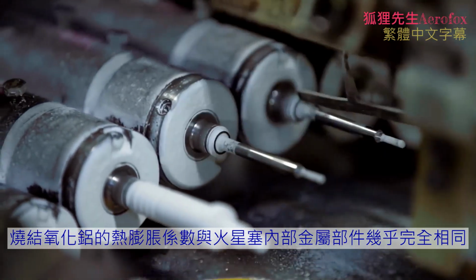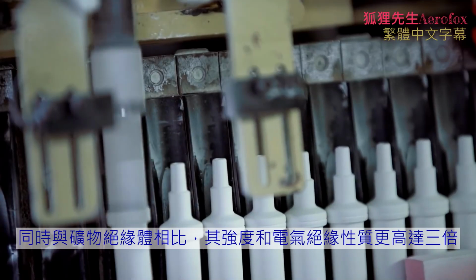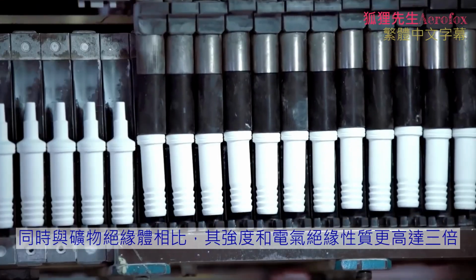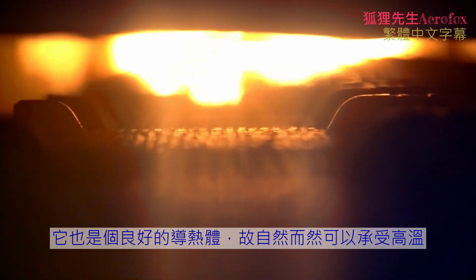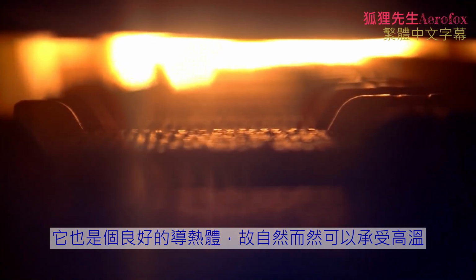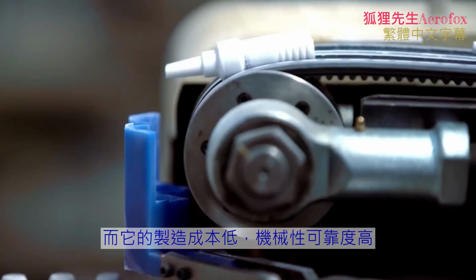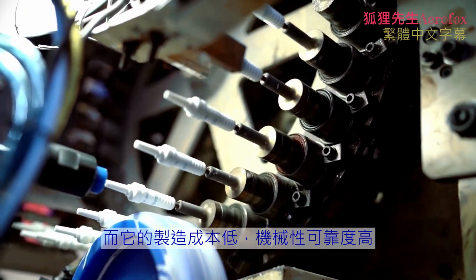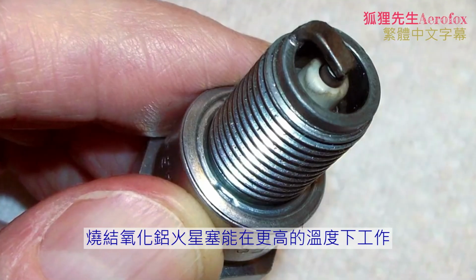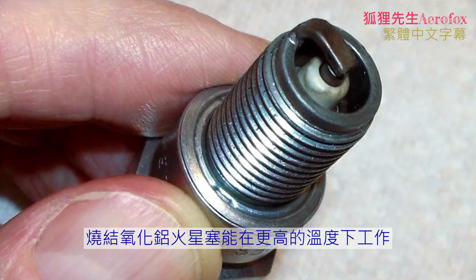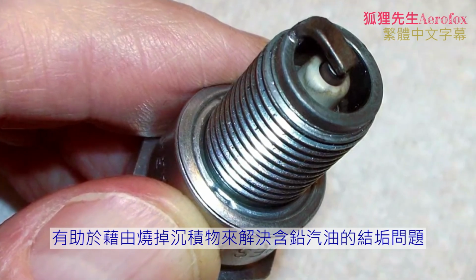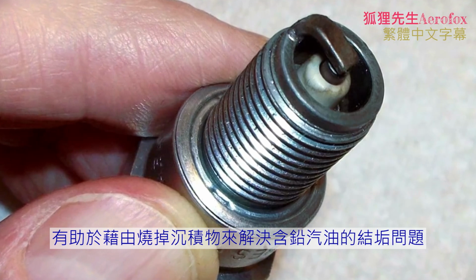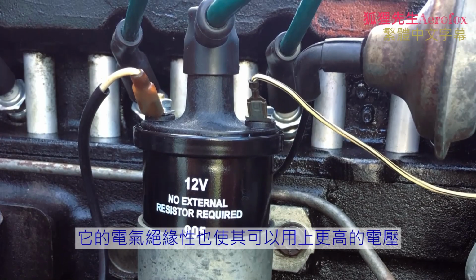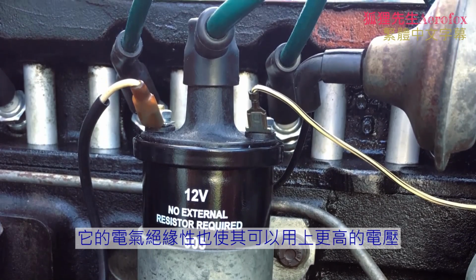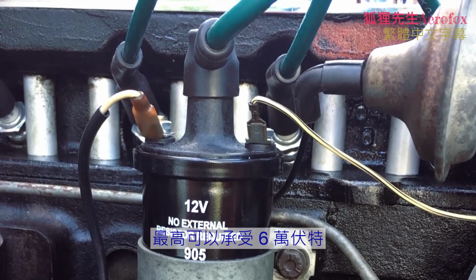as the metal parts within the spark plug, along with three times the strength and electrical insulating properties when compared to mineral insulators. It was also a good conductor of heat while simultaneously being able to withstand high temperatures, and it could be manufactured at low cost and with high mechanical reliability. Sintered alumina plugs operated at much higher temperatures, which helped counteract the fouling issues caused by leaded fuels via deposit burn-off. Its electrical insulation properties also allowed much higher voltages to be used, tolerating up to 60,000 volts.